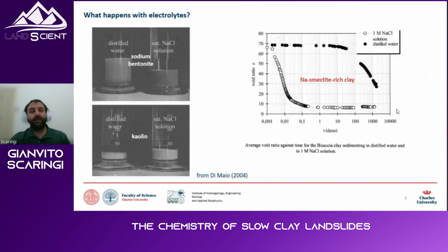So the effect of the surface charge of the clay is felt for a long distance, and this double layer can fully develop. If you have a salt solution, there are cations. There is the sodium in the solution, counterbalancing the surface charge, which is negative, of the clays, and so the diffuse double layers are much shorter. The volume is smaller, and not only the volume is smaller because the structure has a lower porosity, because the particles are basically shrunk, because of the smaller diffuse double layer. Not only, actually, the porosity that is left there is free for water to move.